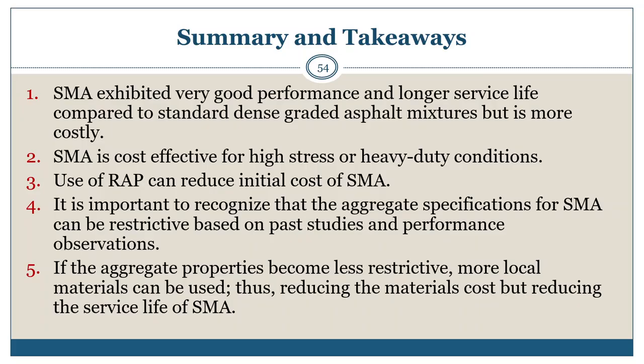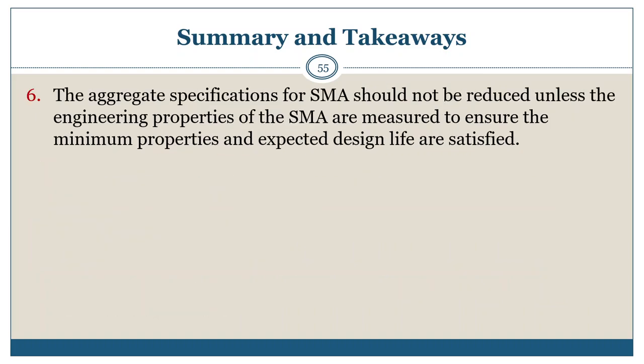The most important takeaway shown on this slide is that SMA does provide and has provided excellent performance and longer service life in comparison to conventional dense graded mixes, and is cost effective, even under very high stress heavy duty conditions. Continuing with the takeaways, the aggregate properties or aggregate specifications for SMA should not be reduced unless the engineering properties of the SMA are measured to ensure the minimum properties and expected design life are being satisfied.